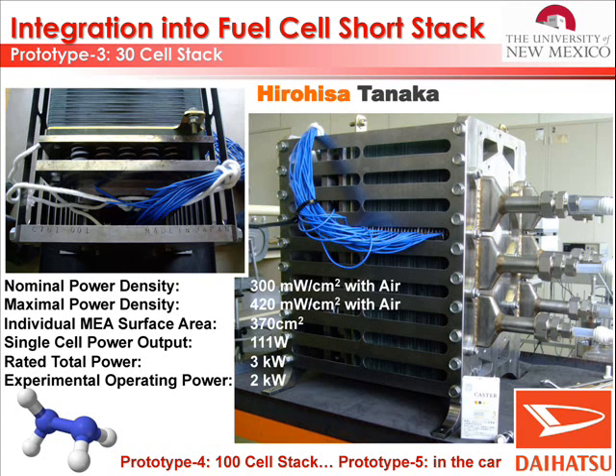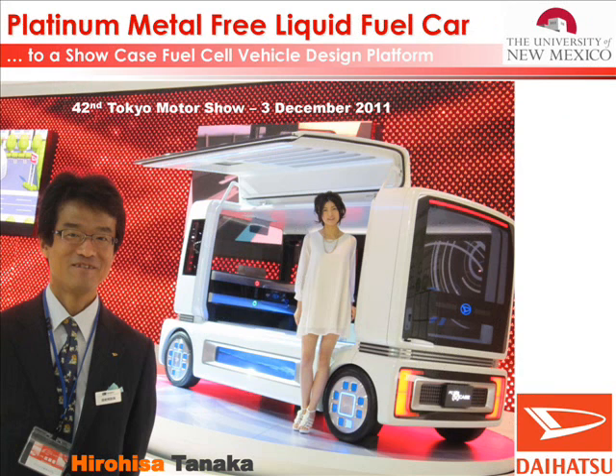A success story for our group came with a phase pure palladium zinc catalyst that we transferred to a nickel zinc similar phase, and a nickel zinc synthesized by spray pyrolysis is our base catalyst for oxidation of hydrazine, and later we combined that with non-platinum catalyst that we also developed for alkaline media, and with the help of a small car manufacturer. Actually, it's a big manufacturer of small cars. So it's a small car manufacturer, Daihatsu Corporation, which maybe some of you know is a component company of Toyota Motor Group. We developed the materials for both anode and cathode for their automotive stack.